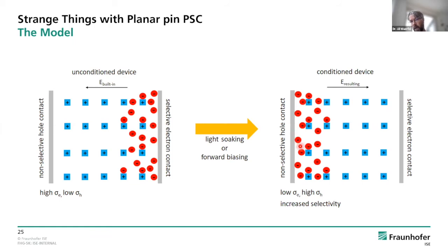If they do, then we have here more or less a neutral situation, or even maybe some excess negative mobile species. This is good because now we have a low conductivity for electrons. They're not attracted, they're repelled by these negative charges, and we have a rather high electrical conductivity of holes. And if you remember what I said, in order to prevent electrons, in this case the minority carriers, from going to the hole contact, a low conductivity of electrons helps, because electrons usually don't go where the electronic conductivity is very low.